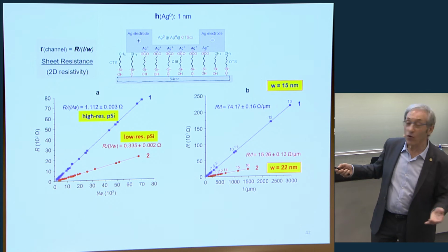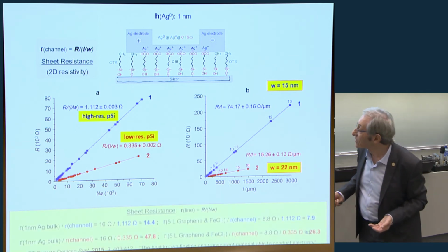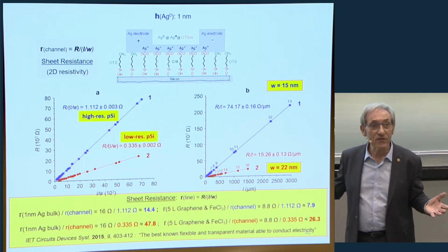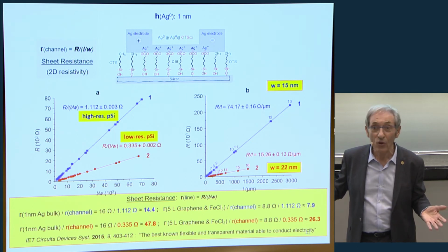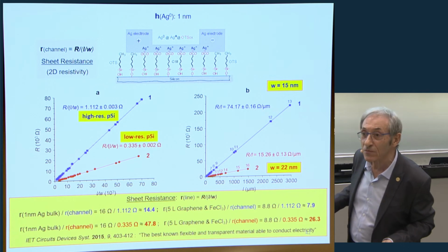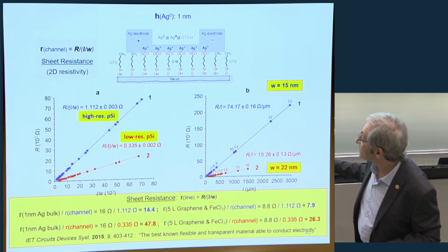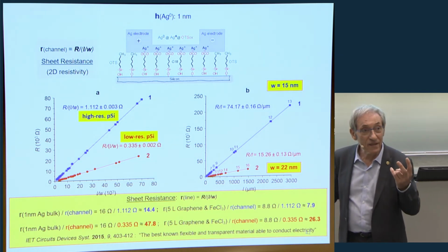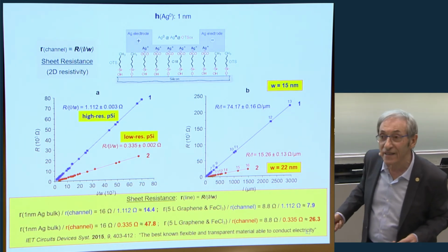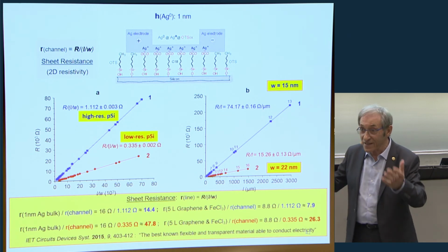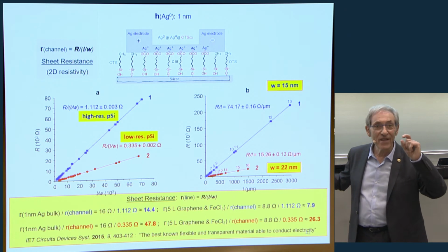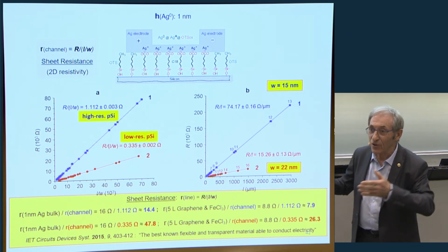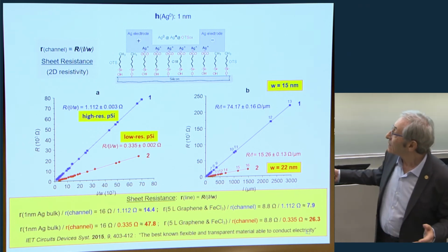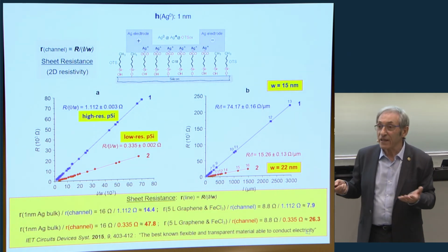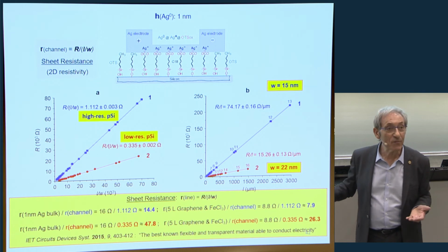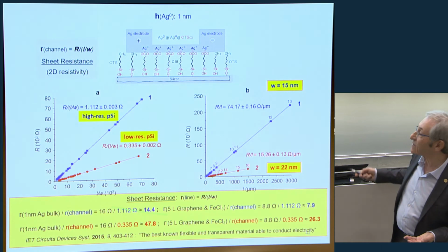So how good is the conduction? Assuming that the conduction is due to the silver, which is formed on the surface, we compare it with the bulk silver. So it turns out that this is much better than bulk silver. In the case of this line, it is about 14 times better than silver. In this case, it's almost 48 times better than bulk silver, if you compare the resistivity. I mentioned the thickness before, it's about 1 nanometer. We know the width, we know the length, and we know the thickness. So these are much better conductors. If you look at the AFM, they look grainy. So the conduction should be poorer, but the conduction is much better. And even if you compare it with graphene, you see that this is much better.